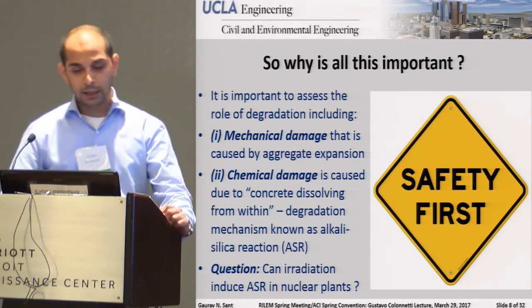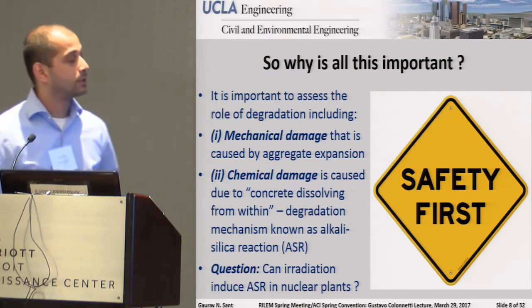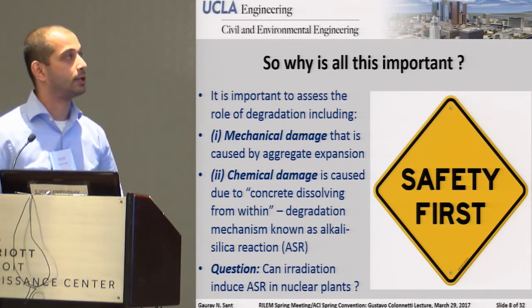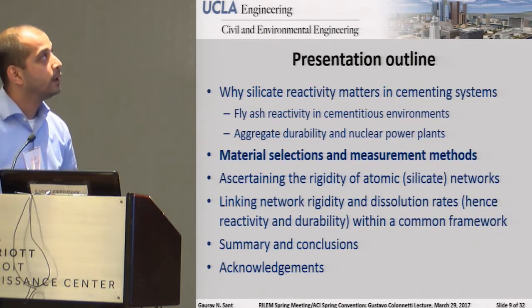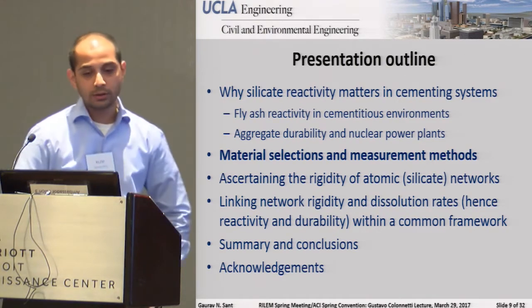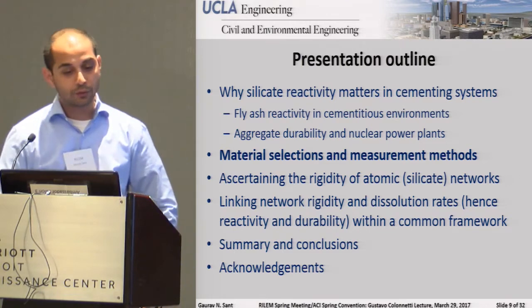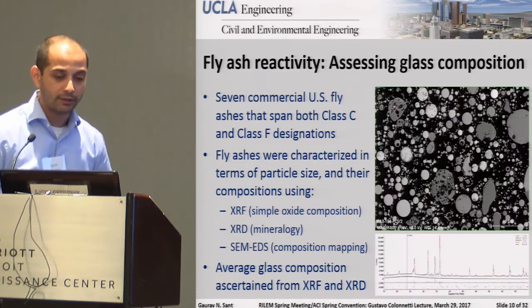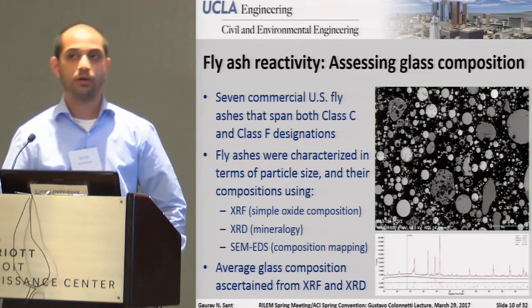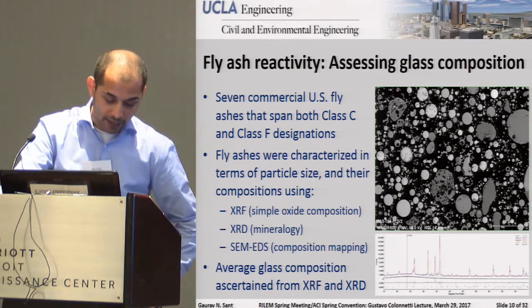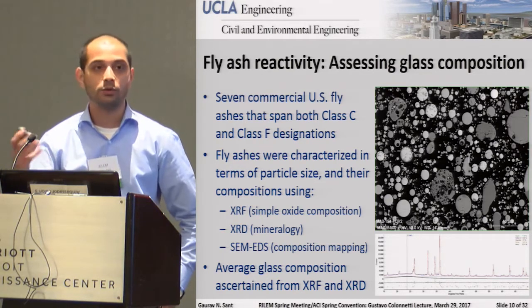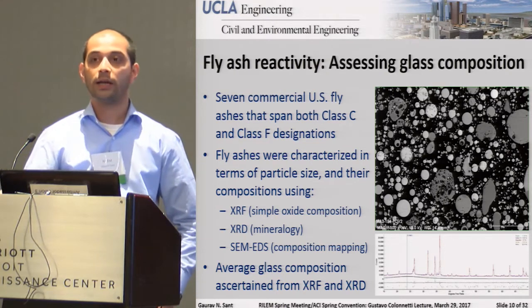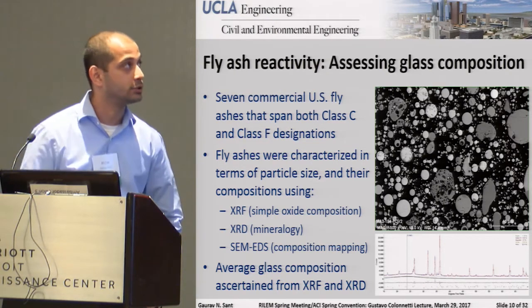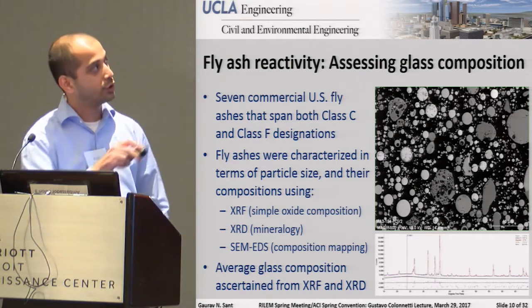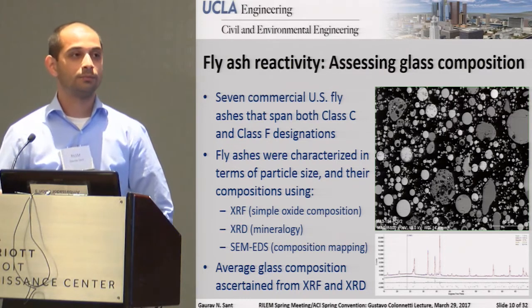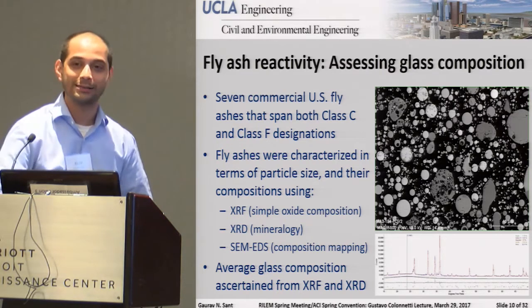So really, going on to how we decided to probe this, it's, of course, good to spend a little bit of time on the types of materials and the methods that we've used. So really, the first thing that I'll talk about is this business of fly ash reactivity. So of course, when looking at fly ash reactivity, we started with looking at about 7 different commercial fly ashes. The fly ashes that we were using spanned the classic ASTM C618 style Class C and Class F designations. So Class C is basically calcium rich. Class F is less calcium rich. They still contain calcium, just not as much.